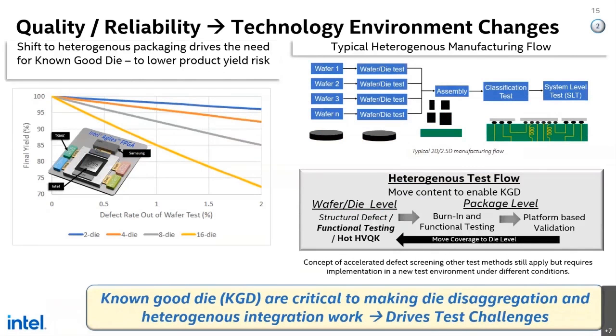We know there are many reasons for moving to heterogeneous architectures. One of them is high defect levels or high failure rates on large pieces of silicon. High defect rates on many pieces of silicon when they're all combined. So one way to mitigate the effects of high defect rates or the low yield, if you see the 16 die case on the right-hand side, the most extreme percent defects out of wafer per test, let's say it's 2%.